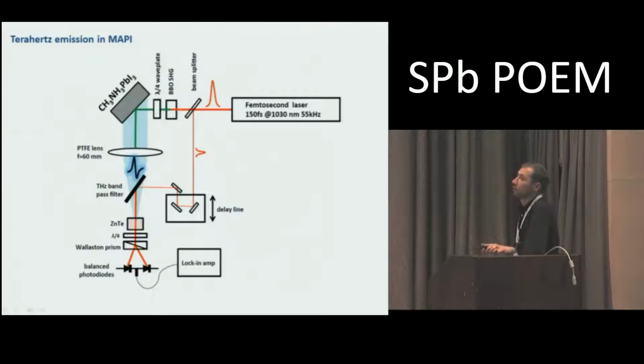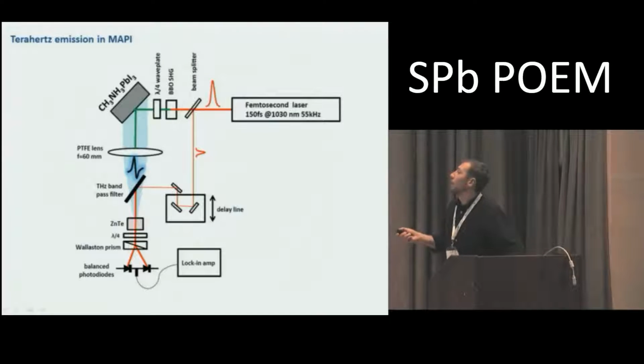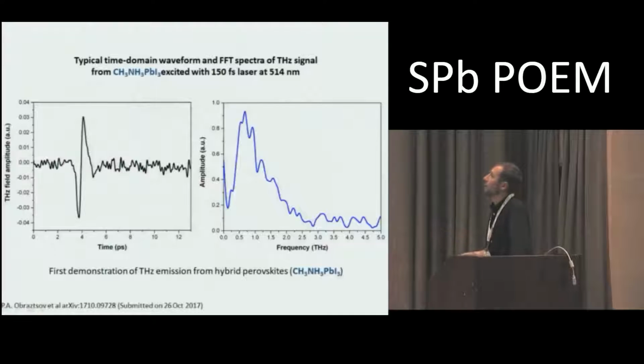And now I move to the terahertz emission experiment. Again, we use pretty similar geometry. However, we have to use the second harmonic to excite our sample because of the special absorption spectrum of this material. We use a traditional TDS system to detect this radiation. And here is the typical time domain waveform and spectrum of the emitted terahertz radiation. So this was the first demonstration of terahertz emission from hybrid perovskites.